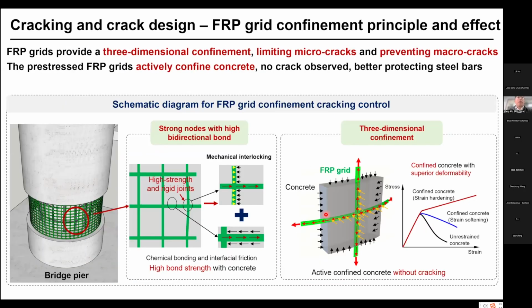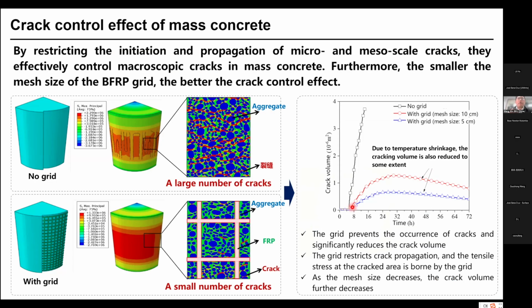Okay, and a very good application is to use the FRP grid placed on the outside of, like, the bridge tower, at the concrete cover layer. The grid is very thin, so although it cannot provide a very strong structural contribution, at this layer it can limit cracking very well because the grid is bidirectional. At the joints, it is very strong because it's FRP. The resin is impregnated in the fibers, and under pressure and high temperature it hardens into an integrated one. It's not like a mesh or some other fiber mesh, so it can control the two-directional cracking very well.